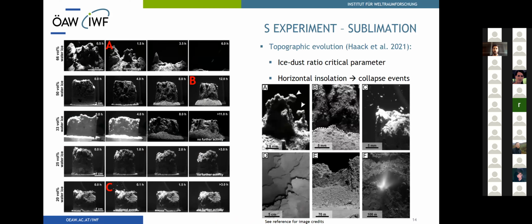A different aspect, which is also related to sublimation, is the topographical evolution of cometary surfaces. As the volatile component of dust-ice mixtures sublimates due to solar irradiation, the remaining refractory component can form different types of features. The collage on the left shows mixtures of fly ash and granular water ice in different ratios, illuminated over extended periods of time. A comparison of the top row, where 88% of the sample volume was water ice, and the bottom row with only 20% water ice, gives a clear indication that the dust to ice ratio is the critical parameter that determines the evolution of surface features.